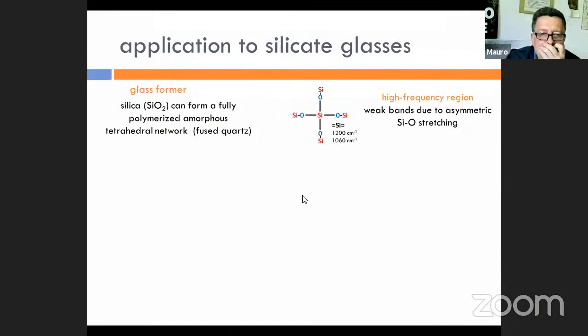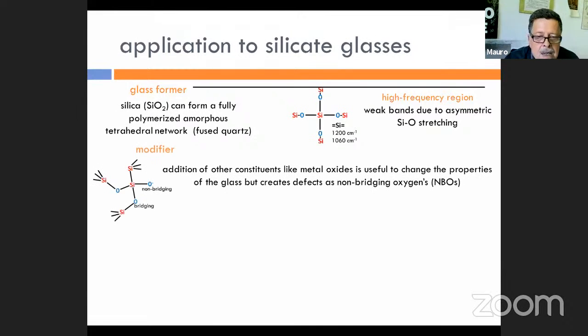Another example, maybe more familiar to you, is the silicate glasses. Silicate glasses are formed by basically a silica network, which is a glass former, which has only weak bands in the so-called high-frequency region. However, this is just the glass former, and usually some modifier is added, a different metal oxide, which is useful to change the properties of the glass. When you add the modifier, you can create some non-bridging oxygen. In the fully coordinated silica network, all the oxygen make a bridge between silicon atoms, while when you add other oxide, you can have some NBO, non-bridging oxygen.